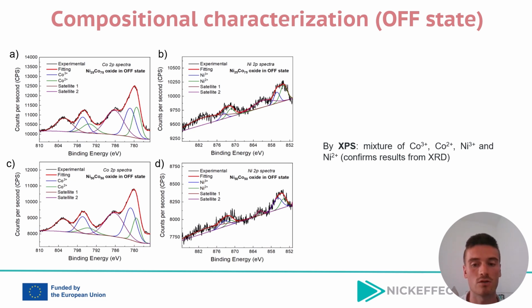...mixed 2+ and 3+ oxidation states both for cobalt and for nickel, which indeed validate the previous findings from the X-ray diffraction analysis, where a mixture of cobalt and nickel oxide was found.